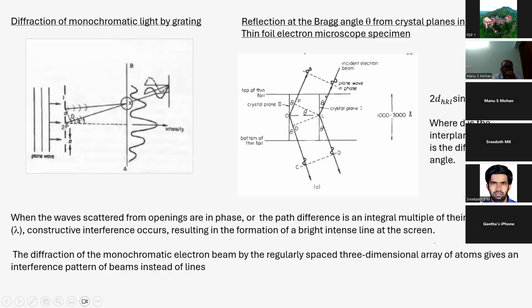As I said, for X-ray, the copper K alpha is 1.54 angstroms. So the only variable term here is D_HKL and sine theta. Sine theta is fixed when you fix it for an angle, particularly in an X-ray source - at a particular incident angle, sine theta is fixed. So those planes will satisfy this equation, those planes will give a reflection whose interplanar spacing will satisfy this equation. When you fix sine theta and lambda, some crystal plane will have a particular D which satisfies this equation.